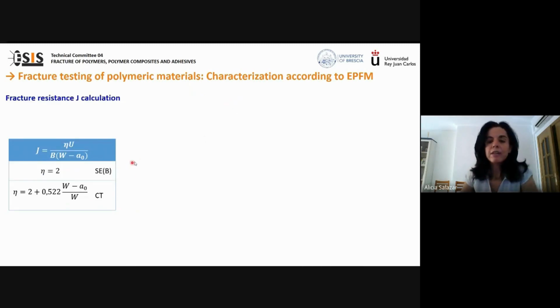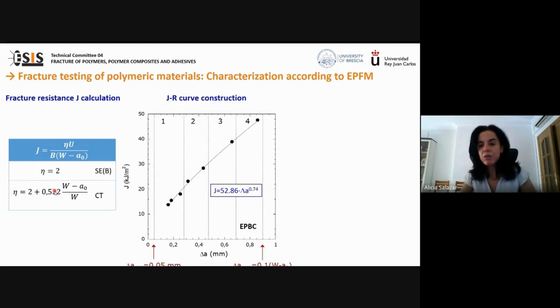For each specimen, the J integral is calculated using this relationship, where U is the energy already described, B is the thickness, W is the width, A0 is the initial crack length, and eta is a calibration factor which has a value of 2 for the 3-point bend specimen, and for the compact tension is calculated through this expression. For the construction of the JR curve, we use the J integral values and the crack extension delta A values to obtain a plot of the fracture resistance against the crack growth.